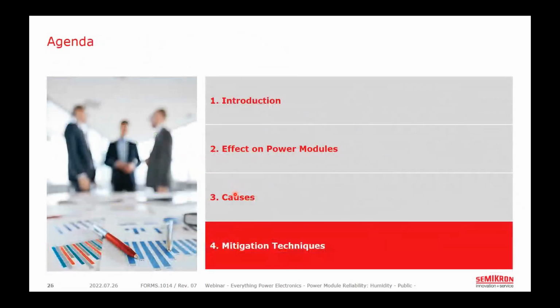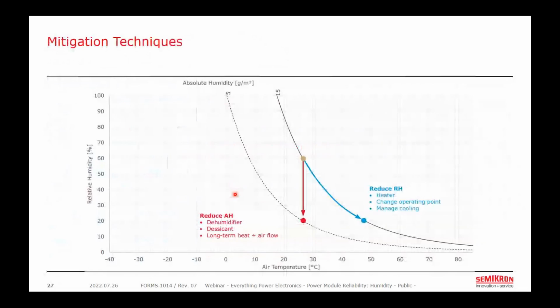Lastly, let's discuss some mitigation techniques. So our goal is really to reduce the relative humidity in those microenvironments in and around the module. And if we return to our simplified IEC climatogram here, there's really two courses of action for us here. So if we're starting, for example, at an environment with a 60% relative humidity, this gold dot here, with 25 degrees C and 15 grams per cubic meter of absolute humidity, we can reduce the relative humidity by increasing the temperature, for example, up to 48 degrees C.